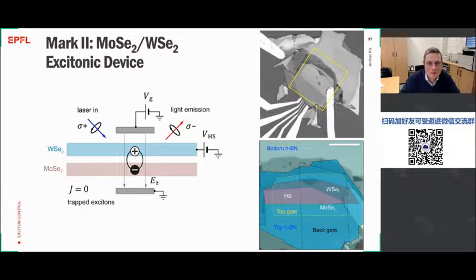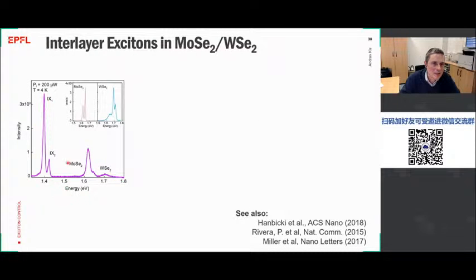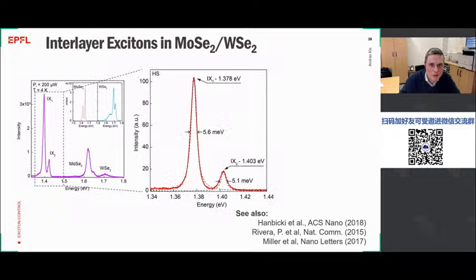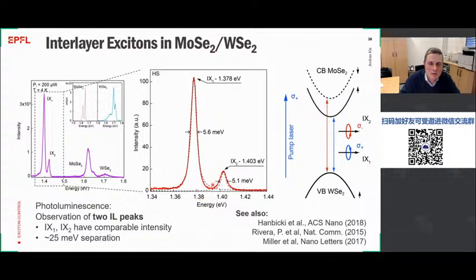So when we made these high quality heterostructures, we saw this very nice interlayer exciton emission and the two characteristic peaks, which are separated by something like 25 millielectron volts. And we attributed these two split peaks in the interlayer emission to transitions between the top of the valence band in tungsten diselenide and the bottom of the conduction band. So this is the standard spin triplet transition, which gives rise to emission with the same polarization.